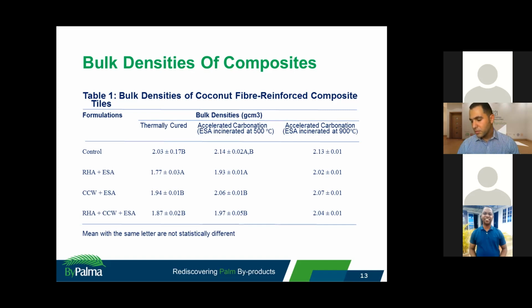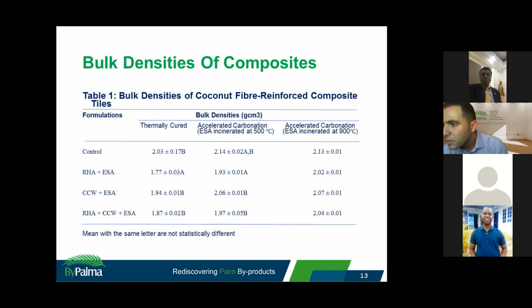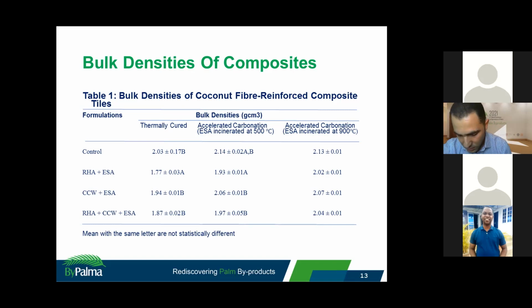Now, thermal curing, what's this thermal curing all about? We are all familiar with the conventional curing method, but this thermal curing is an upgraded method of curing samples, whereby you load your sample in a thermal chamber that has a temperature of about 60 degrees Celsius. The steam from the chamber is going to cure your sample. So we introduced that to upgrade the efficiency of our raw material, because over time it has proven to be better than using the conventional curing method. And these are the values we got for them.